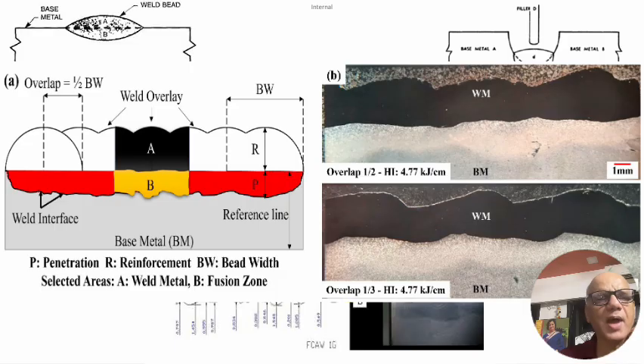So a very uniform penetration, as you see on the top of the surface, we should be able to see at the bottom of the surface also, and not create any anchoring which can lead to failure in our bend test. The top also shall be as uniform and as flat as possible, so that the subsequent layers we can once again deposit with 10 to 12%, 15% penetration. But if this kind of anchoring is going to happen in the subsequent layers on top of this as well, then the dilution levels will be higher, and for the clean chemistry which is required for corrosion resistance or for hardness, you may have to deposit one extra layer, which is going to be expensive.